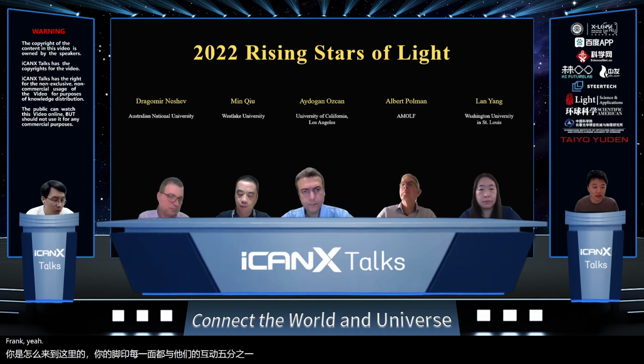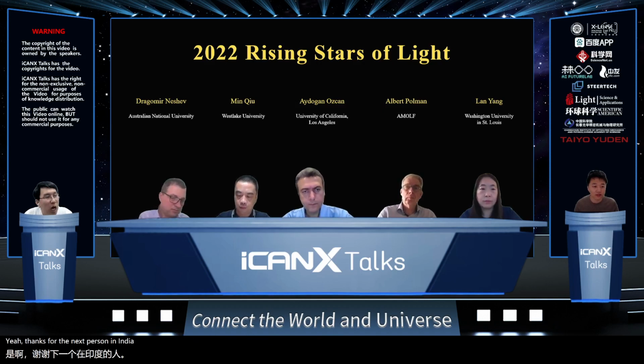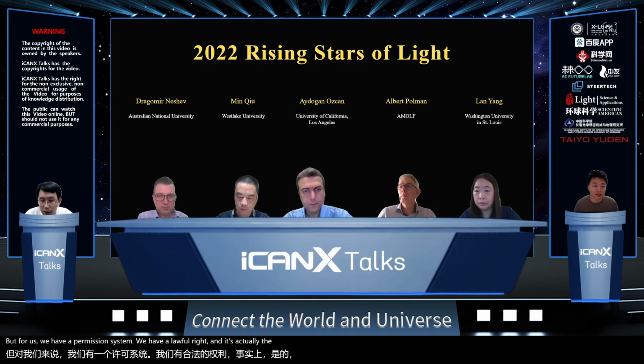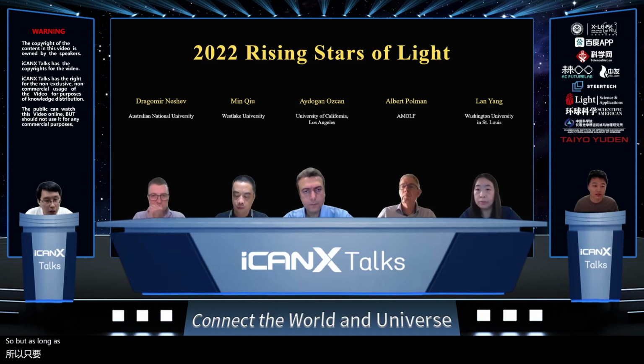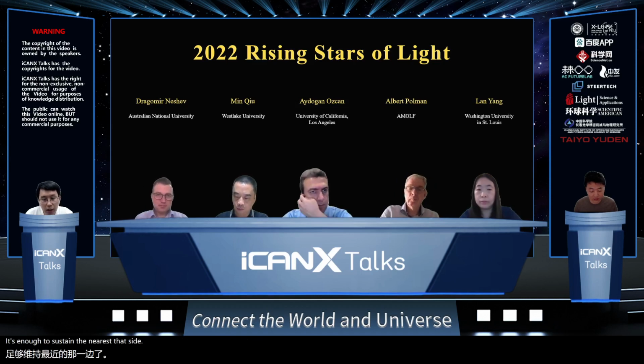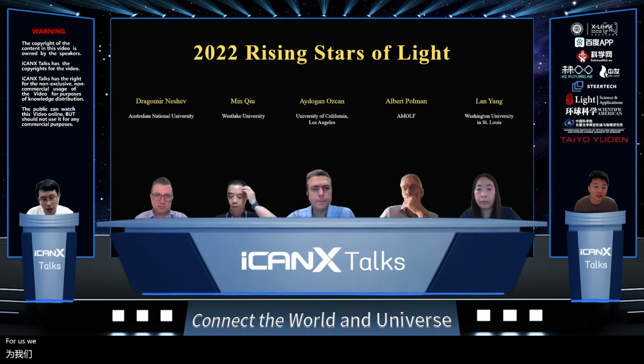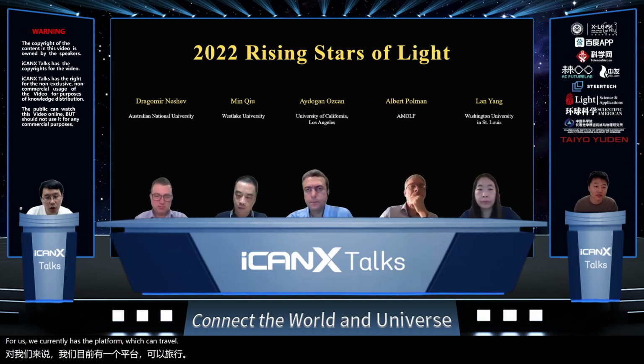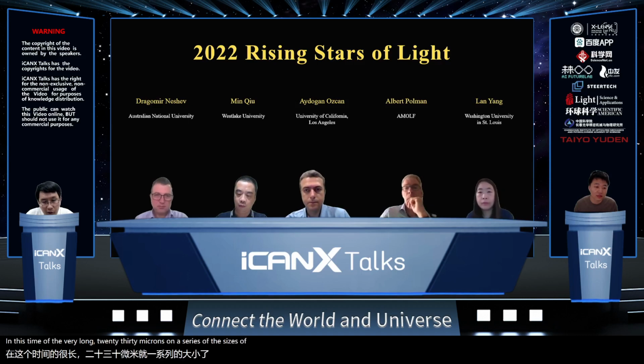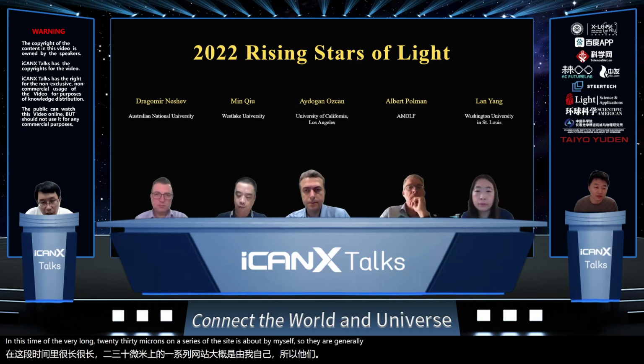Right. Yeah, sure. Thanks for the nice question. Indeed, ideally, you want a fully equilibrium system. But for us, we have a non-Hermitian system. We have loss, right? And essentially, the photon has a finite lifetime. But as long as the polariton lifetime is enough to sustain the nearest site interactions or beyond, everything will be fine. For us, we currently have polaritons which can travel in this cavity very far, 20 to 30 micron. Our nearest site is about 5 micron. So they are generally fine. The lifetime is longer than the interaction time we need.